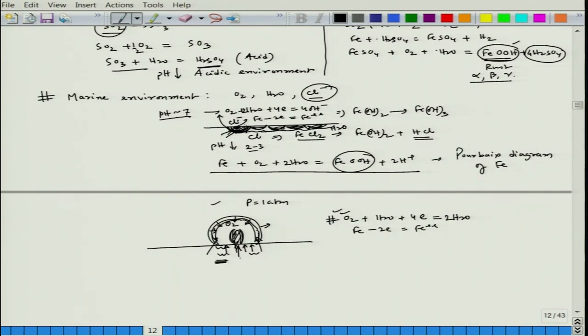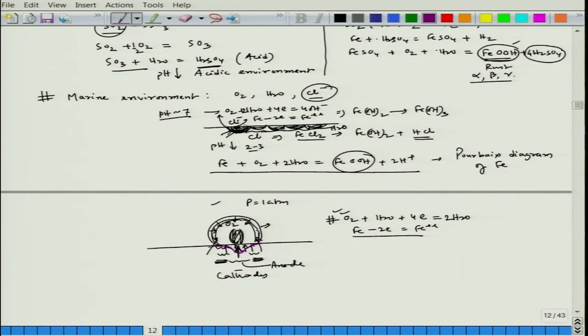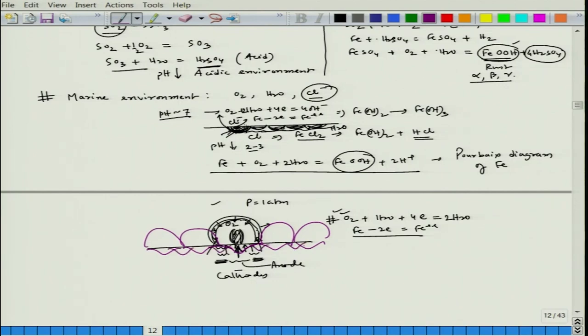The peripheral annular section is in contact with the atmosphere and has plenty of oxygen, so oxygen concentration does not deplete much there. But at the centre, oxygen depletes and no more cathodic reaction can take place. The outer portions are now cathodes and the centre part is the anode. The dissolution reaction happens at the centre, creating a small valley or pit. If rain drops then land at multiple different locations, this corrosion process continues at every portion and eventually gives a kind of uniform corrosion pattern.